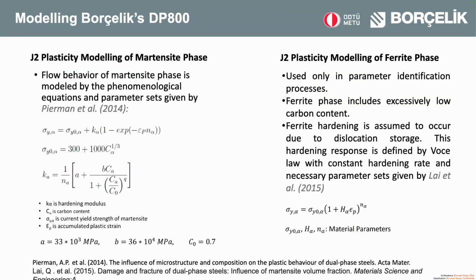So to investigate DP800 steel at Borçelik, first we have to calculate the flow curves of the phases. To do that, we use two different approaches. For the martensite, we use the approach from Pierman's paper. And for the ferrite, we use the approach indicated in the Lai's paper. We calculate the carbon concentration of the martensite using Thermo-Calc. We basically give the program our annealing parameters, and we calculate the carbon content of the austenite, and we accept that it does not change during transformation, and it remains the same in the martensite.